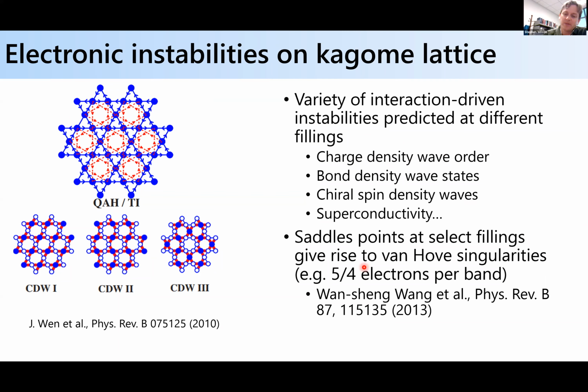predictions that at select fillings, for instance, at 5/4 electrons per band, you can realize saddle points in the band structure at the Fermi level, and these give rise to Van Hove singularities, the nesting between which can drive correlation-driven phases, for instance, charge density wave phases or superconductivity. Okay, and here's an example, a publication which is summarizing that.